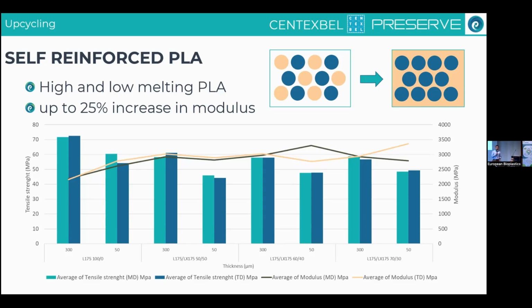The goal here is that you work with a low melting and a high melting point PLA, and by blending these and processing them at the right temperature, you once again get these microfibrillar structures, as you saw in the last picture. But this time, instead of using polyethylene and polyamide, we use a low melting PLA and a high melting PLA to get these self-reinforced structures. And here we see an increase of about 25% in modulus for these self-reinforced blends compared to just the virgin PLA.